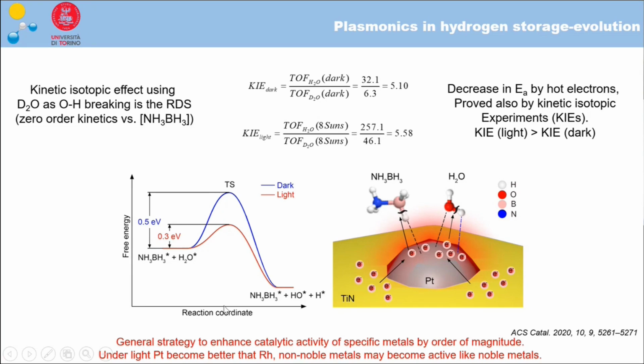And overall, this was to show that using this strategy, we can enhance by one order of magnitude the activity of a metallic catalyst with respect to the dark conditions. And for example, this can be interesting if we think that if we substitute, for example, platinum with non-noble metals, and using this kind of strategy, we could bring the activity of non-noble metals to that of noble metals.